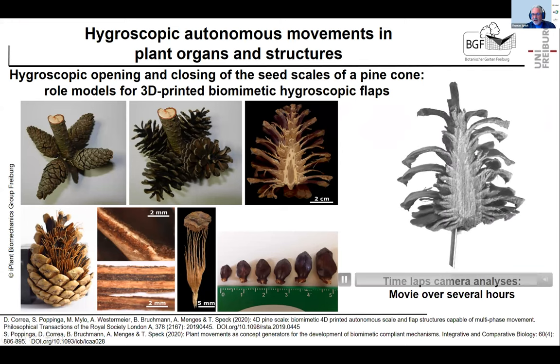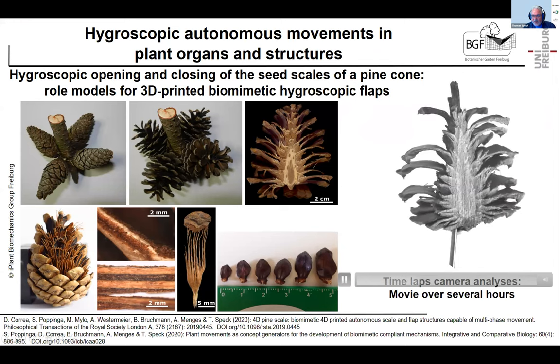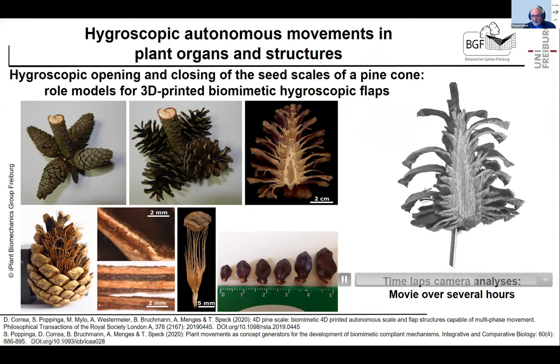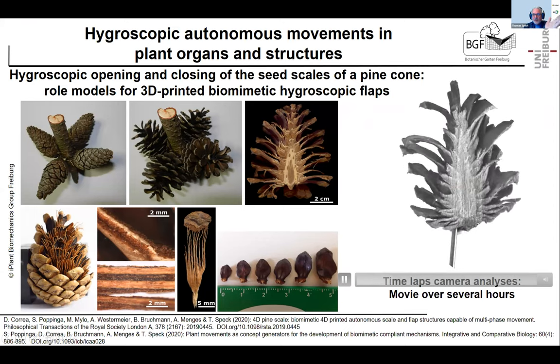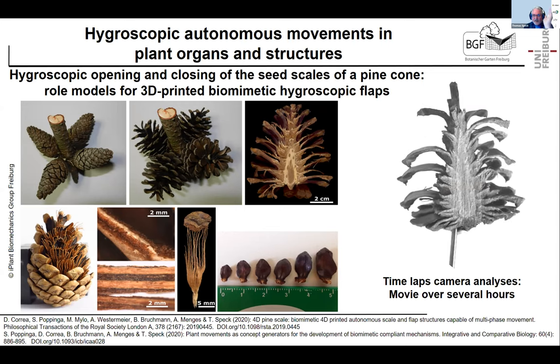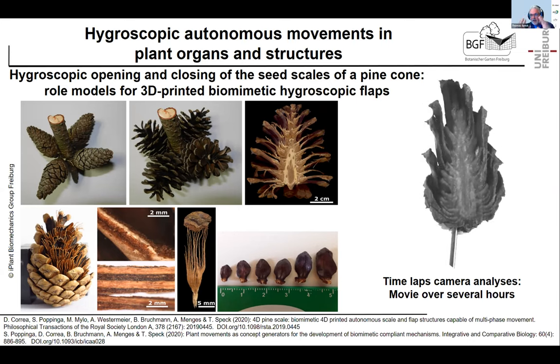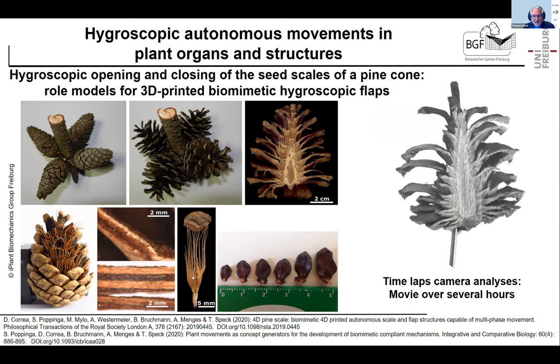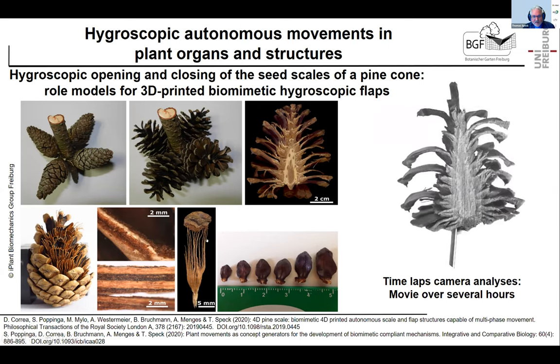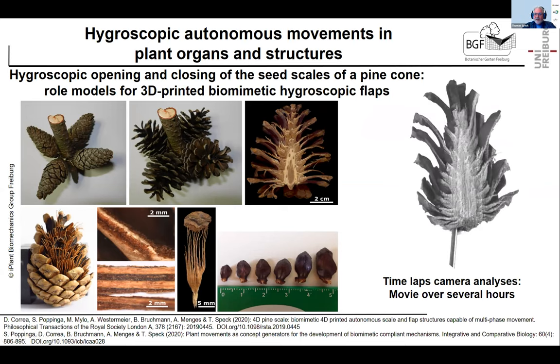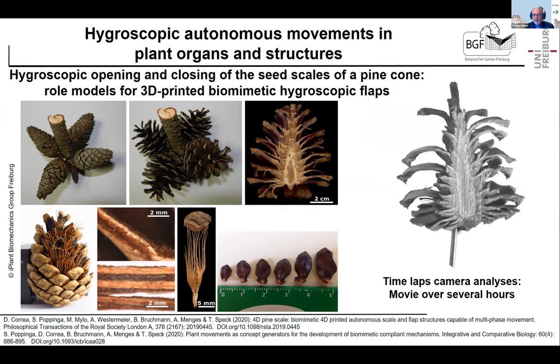The pine cone scales you can visualize as bilayers. They have a resistance layer on top with fibers and an activating layer with sclerite cells at the base. If the sclerite cells swell when it's wet, they close the pine cone scale. If they shrink, they open it. In reality, we have just published papers on that. It's more complicated. It's a hierarchically structured system, with fibrous structures inside which themselves act as bilayers. But what's important for us is to think of one of these scales as a bilayer, opening if it's dry, closing if it's wet.